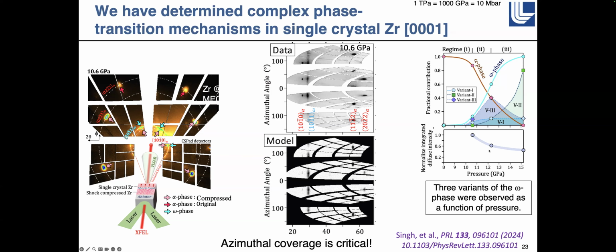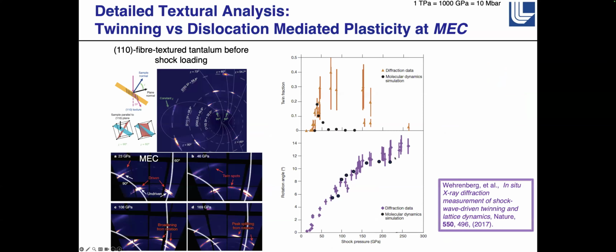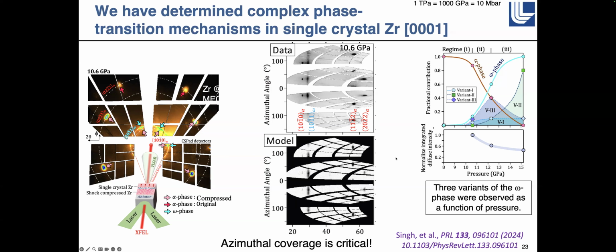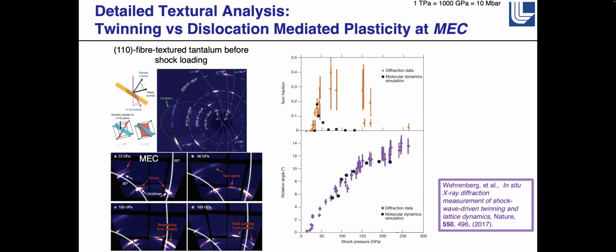So it was really interesting because in previous experiments, people weren't able to tell what the preferred mechanism was from dynamic experiments. But we were able to show that it's not just a single transition. This was another experiment led by Chris Wehrenberg that was really neat. We used purposely fiber textured tantalum, and because of that, we could see just kind of spots. He was able to say why we see these spots based on the fiber texture, and then when we shock compressed it, we got twinning, and we got rotation.